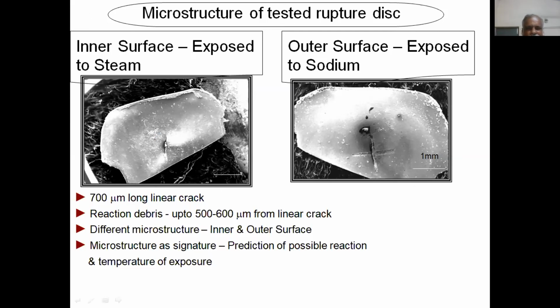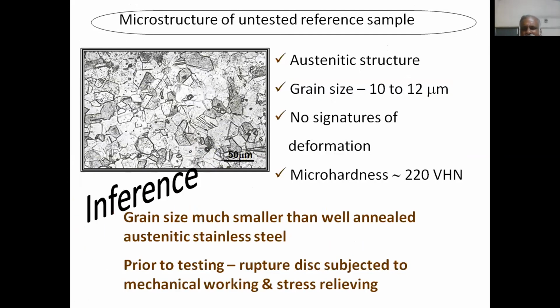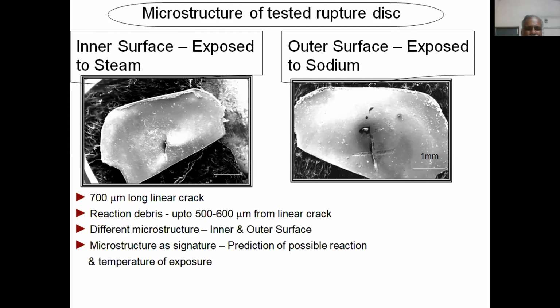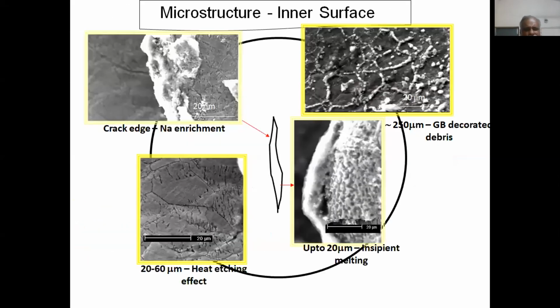The inner surface exhibits a linear crack. On the outer side you could see the plus mark, and you could see debris thrown out, white debris on either side, a 700 micron long crack, with debris thrown around up to 500 to 600 microns. We examined the microstructure in detail of these two discs, on either side. We could see what the microstructure evolution could be as a function of this exposure to the possible reaction of sodium and steam. The edge contained debris of sodium oxide, and the edge also exhibits an incipient melting condition, and at a distance of around 250 microns, a lot of decoration of the grain boundaries.